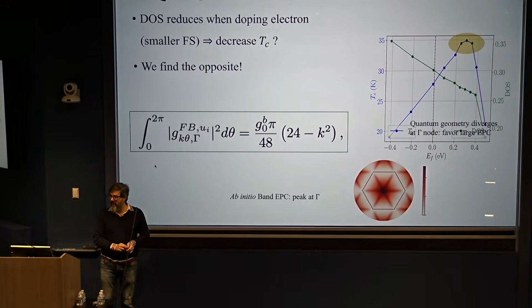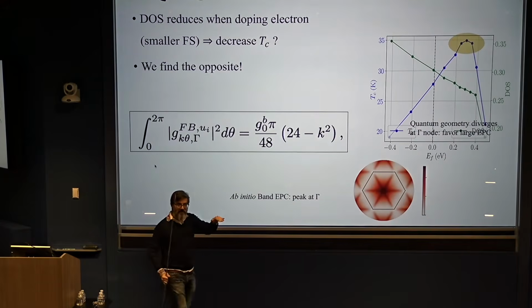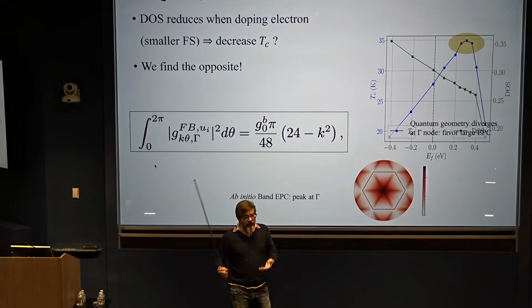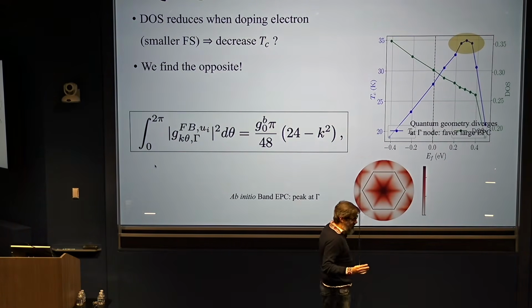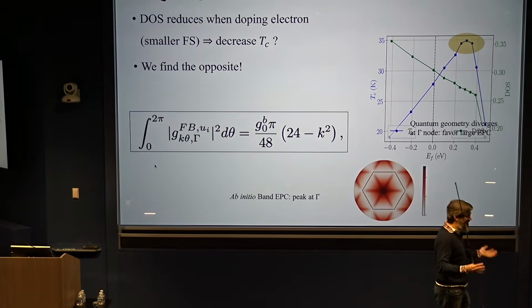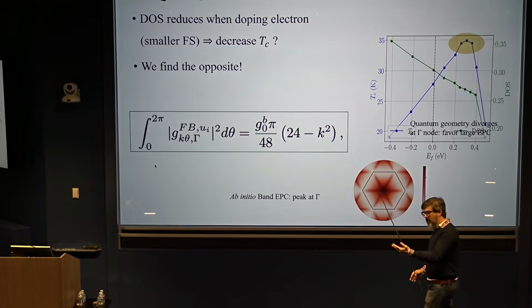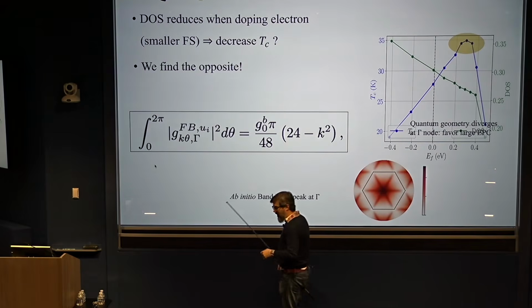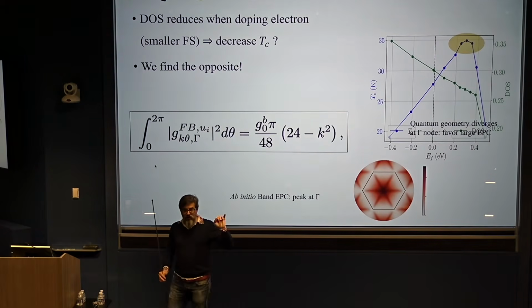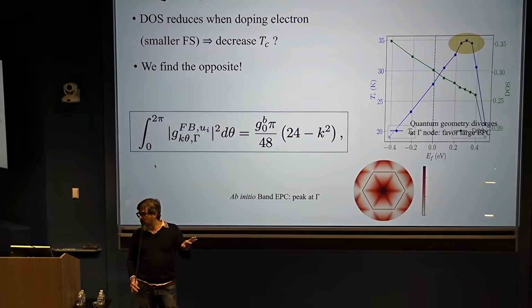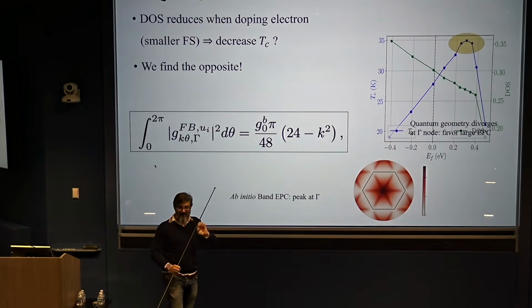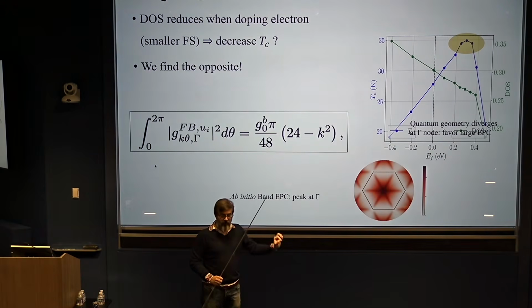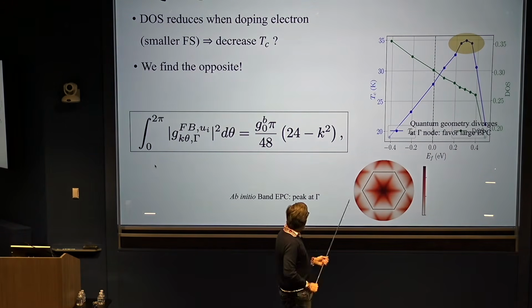This prediction says the following. I'm going to dope the system now with electrons, right? So you use analytics usually just when the phase space is too large and you can't do computations for every little parameter in a phase space. So now let's use doping here as a parameter. But I want to make sure that we understand that this doping is doping like the 2D people, like Stefan, would dope his systems by gate doping. Now that cannot be done in MgB2, but it's important that that's the calculation being done. We're not adding impurities. And I'll come back to that later.